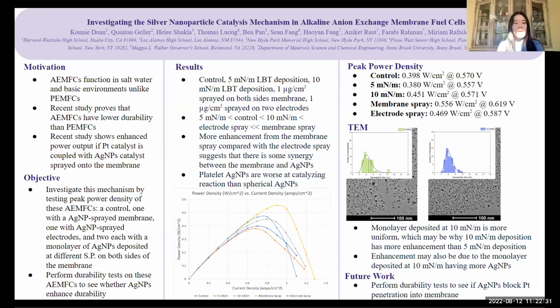AEMFCs are a type of hydrogen fuel cell, which all produce power with the only byproduct being water. AEMFCs function in saltwater and basic environments, unlike PEMFCs. Recent studies prove that AEMFCs, however, have lower durability than PEMFCs because the platinum catalyst penetrates into the membrane. Recent studies also show that the power output is enhanced if the platinum catalyst is coupled with silver nanoparticles that are